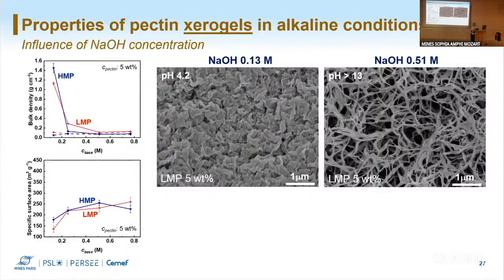If I may comment on this, because we see this structure for aerogels as well. They are supposed to preserve the structure, but they still have shrinkage and they don't really preserve it. So already before drying, the structure is probably not ideal for super insulating properties. Of course, the drying process needs to be studied, but to reach better insulating properties, the focus should be elsewhere. You shouldn't try it on the pH 13 sample. You should try it on the pH 7 sample or something in that range.